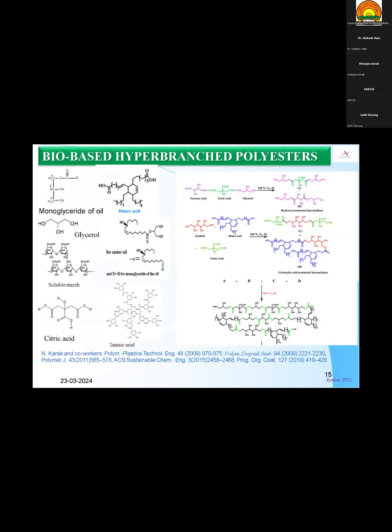Thus, in our research, we have started our journey with hyperbranched bio-based polyester systems, because polyester means esterification reaction, the simplest organic reaction, and polyester outranks, about 54%, in the coating and paint industry. In addition to that, polyester can be used as a film, as a fiber, to make foam, to make hot melt adhesive. So wide applications are possible from this polyester. So we have used different types of bio-based raw materials like monoglycerides of the oils, dimer acid, glycerol, citric acid, tannic acid, starch, to get the hyperbranched polyester system.